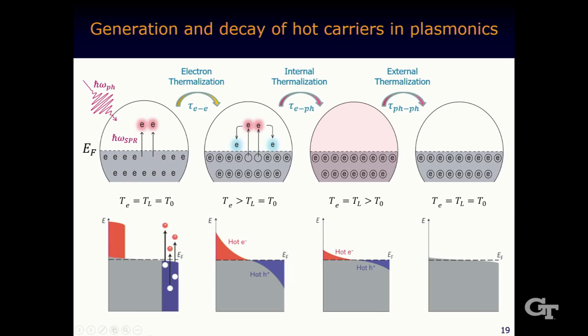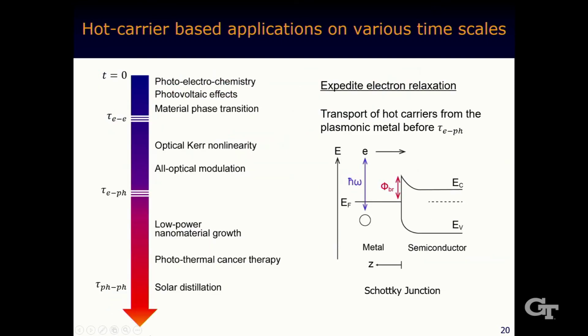Given even longer time, the electron will exchange energy with the lattice through electron-phonon scattering. So now the electron will further lower its temperature and increase the lattice temperature through this so-called internal thermalization. And eventually, using nanoseconds or even longer, the entire system will reach back to equilibrium with the environment. So this electron dynamics is very important for different applications of hot carriers.